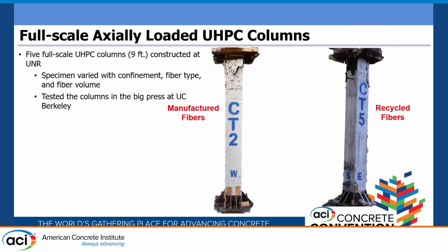So after we did the mechanical characterization, we went to the full-scale columns. I developed 5 full-scale columns. The dimensions are 9 feet tall, and the cross-section is 12-inch by 12-inch. These specimens were varied in terms of the confinement type, so we chose more confined or less confined, and also the fiber type, comparing the manufactured fibers with the recycled fibers, and also the fiber volume.